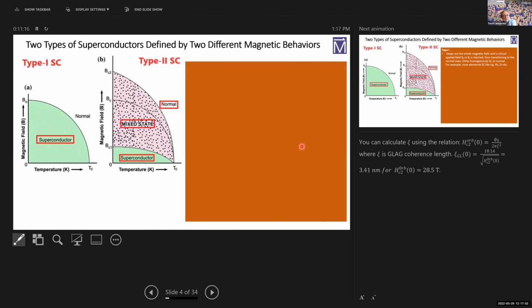Now, there are two types of superconductors defined by two different kinds of magnetic behavior. The elemental superconductors, so-called type 1 superconductors, have this kind of fairly standard second order phase transition curve where you have a superconducting state here and then a normal state out there. There's a critical field, which is temperature dependent, and then you get this transition. And neglecting situations where there's an inhomogeneous demagnetization factor, essentially the material is superconducting here and it excludes flux, as I showed, and up here then the flux enters.